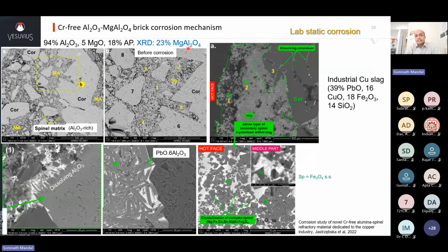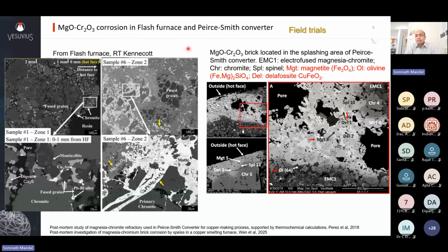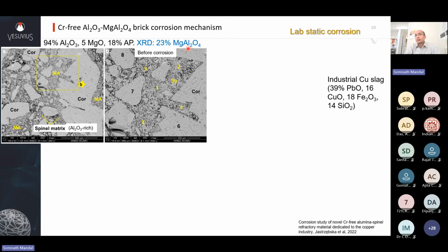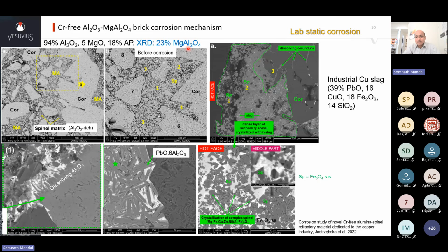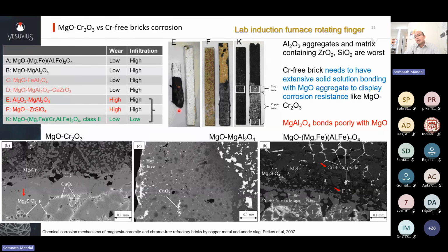So one thing is theory, right? From theory, you know that magnesia is basic, the slag is acidic, so it should react, whereas alumina is amphoteric or neutral, so it should react less. But in reality, that's just a preliminary indication. What happens is that your alumina gets washed away by the slag due to formation of new phases. In this case, you see lead alumina based compounds, lead hexaluminate. Because of these compound formations, the reactions happen even with this slag, and because of that, you end up losing your alumina a lot faster than your magnesia based materials.